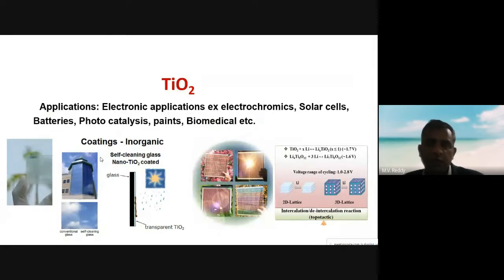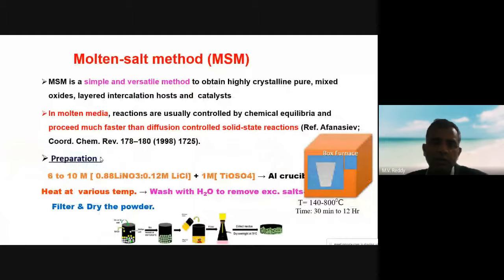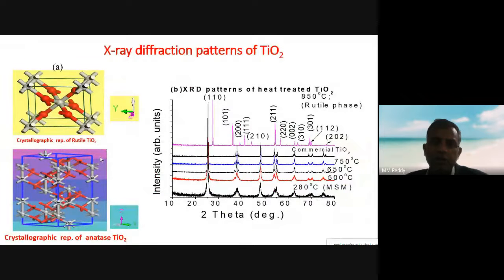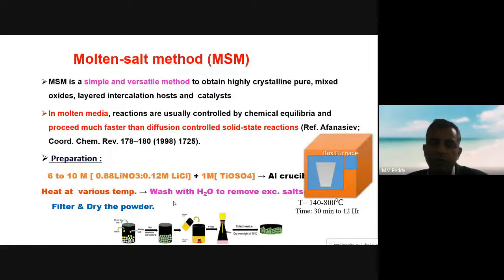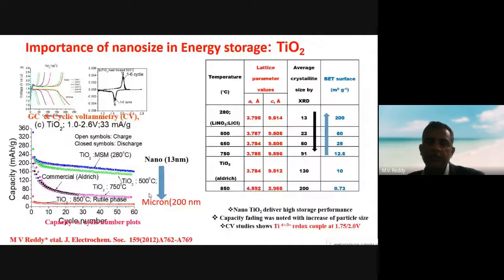Since there are 5 minutes, I'll go through another important one, for example TiO2, which all people are familiar with. What I'm mentioning is that with the molten salt approach, you can try to prepare samples with high surface area. As you can see, 200 square meters per gram with low temperature. Again, we can see the difference in the energy storage performance, and the variation of the crystallite size, etc.